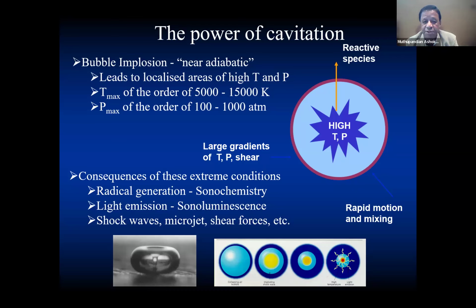Again, when you have high temperatures and also chemical species like water, oxygen, nitrogen, etc., you can induce chemical reactions. I will come to that point a little bit later. In addition to this radical generation and light emission, there are also shock waves and other shear forces generated. For example, because there's a large volume change, the pressure inside the bubble can be of the order of 100 to 1000 atmospheres. After the collapse, that pressure is released back into the solution as a shock wave.